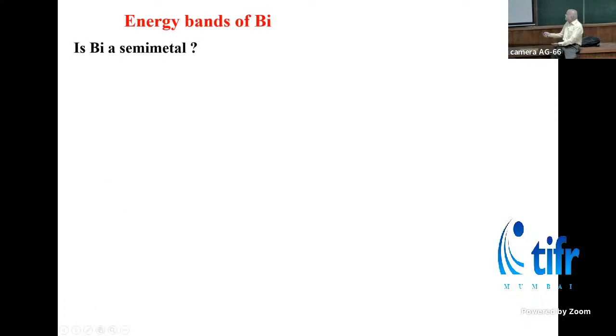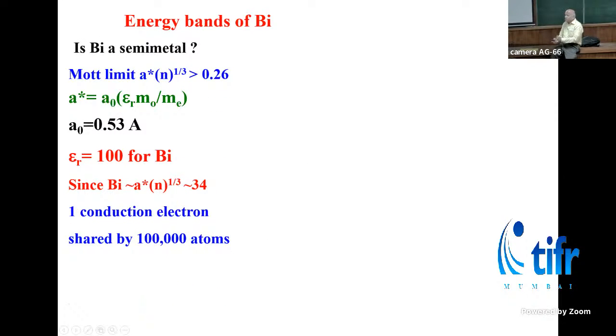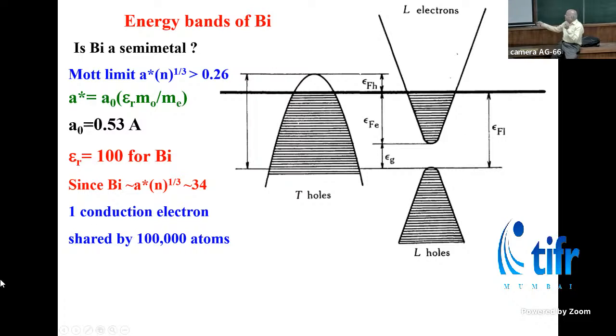And since the first question you ask is, with such a low carrier concentration, is bismuth a metal or a semi-metal? The important thing is the criterion given by Mott, called the Mott minimum metallic conductivity. That is, with an effective Bohr radius, the carrier concentration should be greater than 0.26.